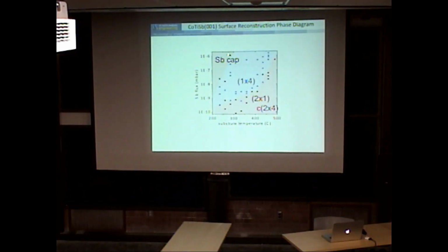The nice thing about growing this material is we can grow with excess antimony if we grow hot enough, because it doesn't stick unless it reacts. And then we can actually get a surface phase diagram, depending just on the antimony flux and substrate temperature.